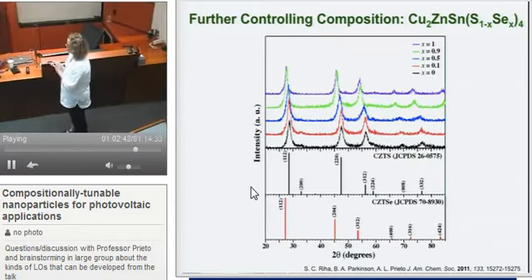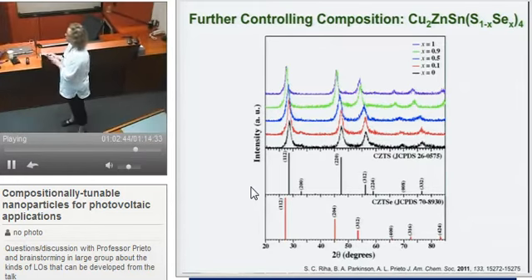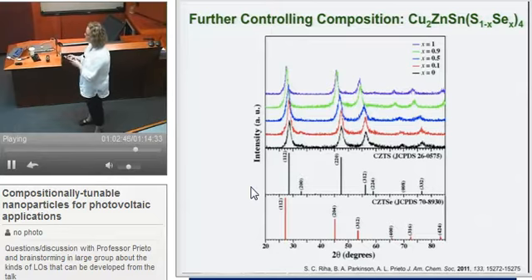So here are the data just for the X-ray diffraction. Keeping in mind it has all the challenges I showed you before, but at least the lattice shifts are important here. In black is the 100% sulfur. The red is 10% selenium, 50% selenium, 90%, and 100%. And you see a shift to lower 2 theta, which means a larger d-spacing.